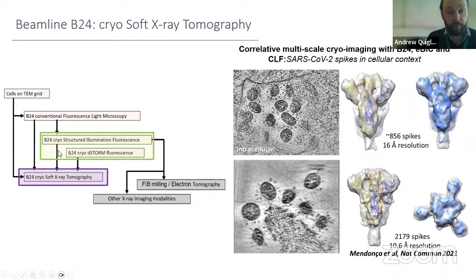We can then transfer those samples from the fluorescence microscopes, and the same grid can then go onto the soft X-ray tomography beamline for analysis using X-ray tomography. Obviously, some of the advantages here are the deeper penetration of X-rays over electrons. But equally, those grids at the fluorescence step could also go in the direction of FIB milling and electron tomography. The example on the right is a combination of correlative multiscale cryo-imaging with soft X-ray tomography alongside electron tomography, as well as fluorescence and light microscopy approaches, where the CLF have been able to look at the life cycle of SARS-CoV-2 within the cell and look specifically at what's going on with the spike protein at different points in the viral production process.